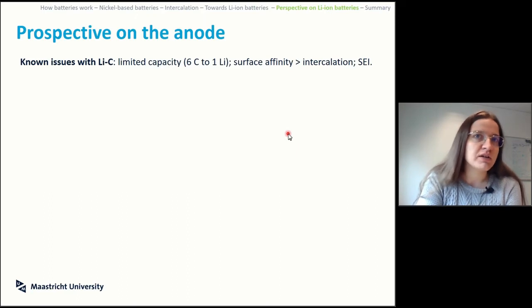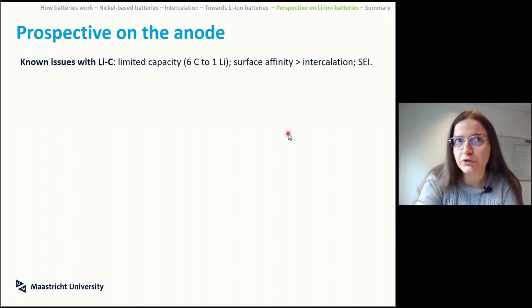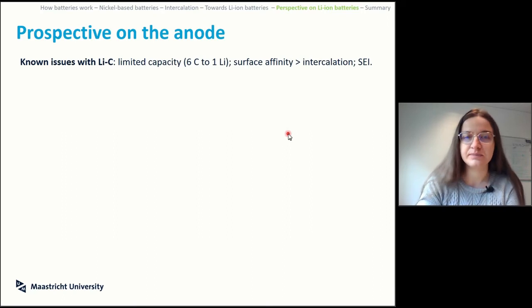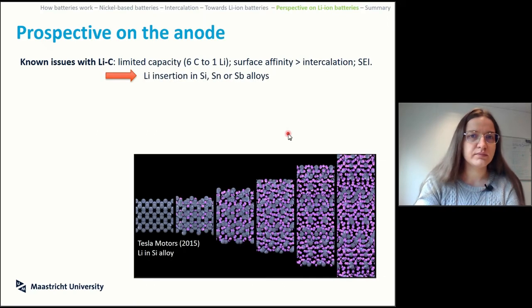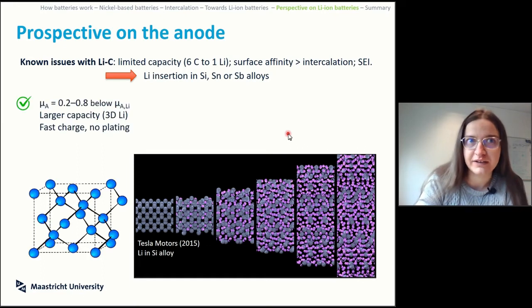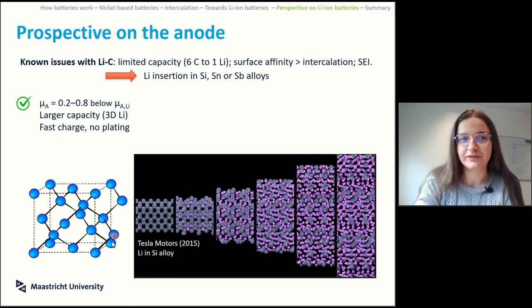And also you have the solid electrolyte interface, not necessarily a problem depending on how you use your electrolyte, but you need to remember that it's a thing, it's there, it exists. So the alloys can be back at this point. We could introduce our lithium into something else, and our very notorious diamond cubic alloy structure of silicon, tin, antimony, stuff like that, alloys that have these types of spaces in between, and this is sort of a 3D network in which the lithium could move within these empty spaces.